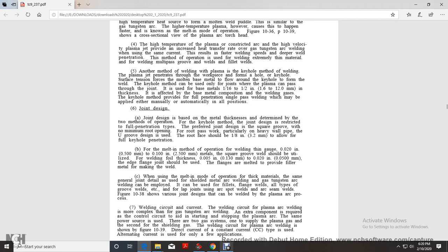full keyhole penetration. For the melt-in method of operation, welding thin gauge metal of 0.020 inch to 0.100 inch, a square groove weld should be utilized. For welding foil thicknesses of 0.005 inch to 0.020 inch, the edge flange joint should be used. The flanges are melted to provide filler metal for making the weld.